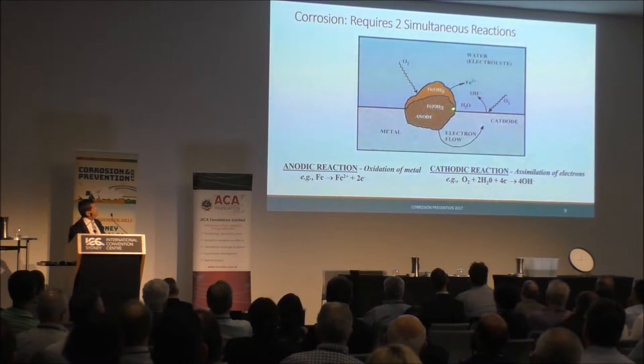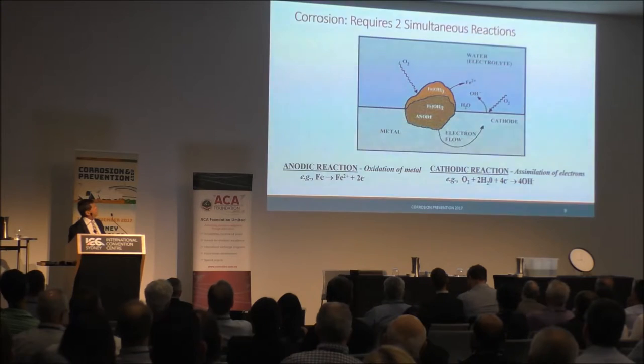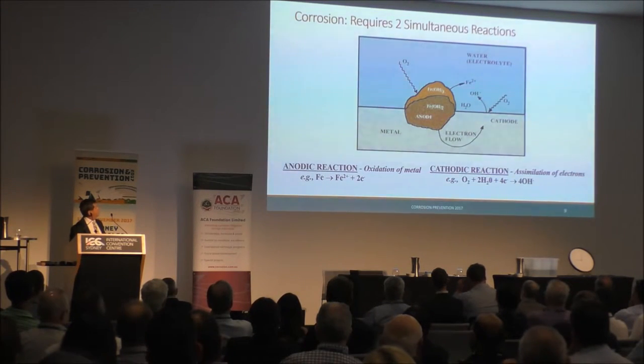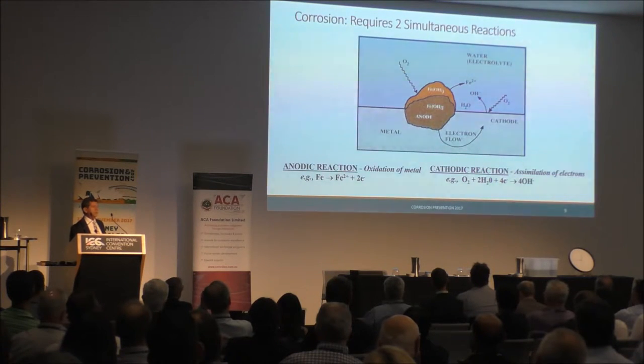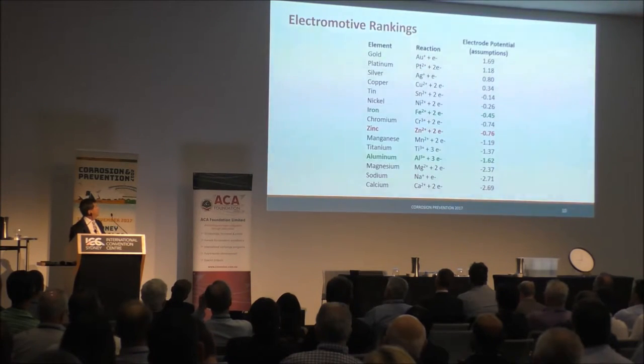So the oxidation of the metal takes place here, you form corrosion products, and it's driven by this cathodic reduction process someplace near the anodic site. The presence of water is important in many applications of paints on corrosion, and if we can adjust or affect any one or several of these characteristics, then our paint might be able to stop or mitigate the corrosion process.